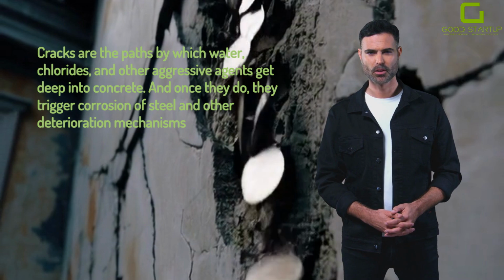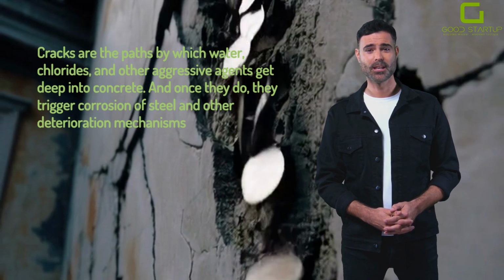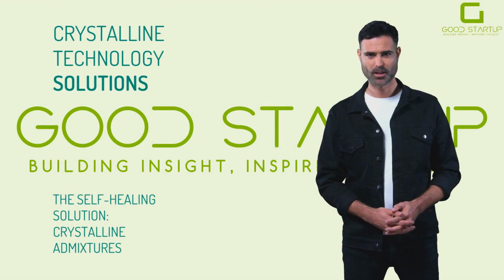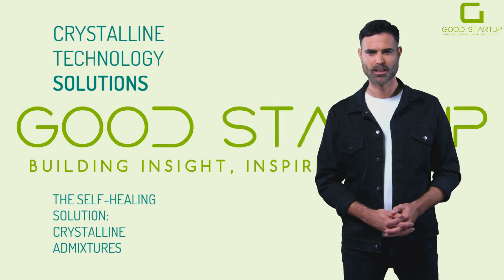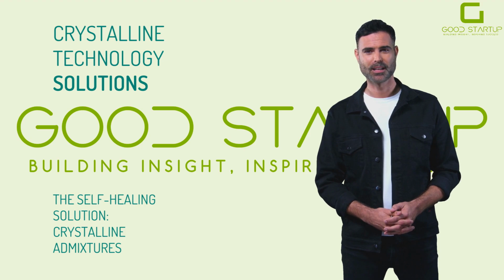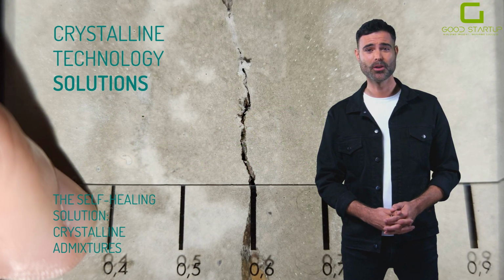Traditionally, that meant extra rebar, thicker covers, external membranes, etc. Today, we have a far more elegant solution: crystalline admixtures that turn the concrete itself into a self-healing, watertight material. The self-healing solution, crystalline admixtures. Crystalline waterproofing admixtures are a game changer for concrete durability. Added directly into the concrete mix, they enable concrete to heal its own cracks and prevent water ingress.